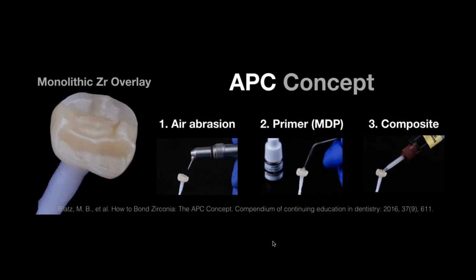This was published by Dr. Blatz back in 2016, and basically understanding that zirconium oxide is a material that is not sensitive to hydrofluoric acid etching. So we need to clean it in alcohol in the ultrasonic after doing the try-in, and then the first step would be the air particle abrasion with aluminum oxide particles of 50 microns at a low pressure of 2 bars. Once we do that, we're just going to apply a little bit of air from a dry air source, not having water there. And once we clean it, then we will apply the specific primer.